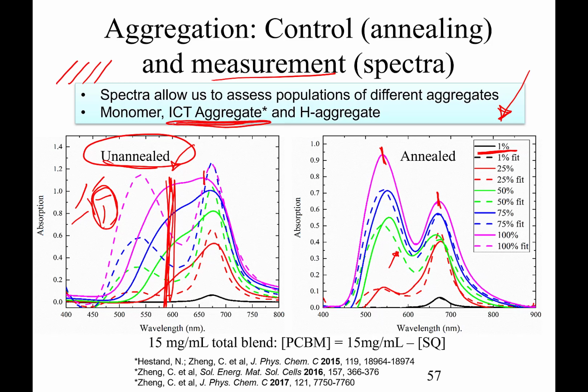We can find a whole bunch of papers from my group where we look at this intermolecular charge transfer aggregate, and we confirm that that double hump feature is that aggregate. We can also see a dipole-dipole H aggregate, and this H aggregate is what we're seeing in this region at around 600 nanometers. Okay, so where we're looking is right in here. That's a symbol of that H aggregate, and of course the monomer is down here at around 675 nanometers.